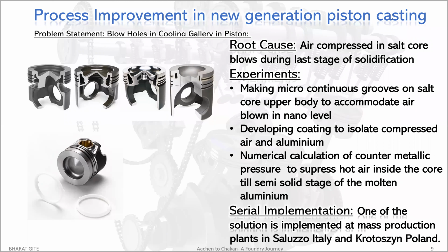Defects such as blowholes were observed in the upper side of the cooling gallery, and after a lot of effort, root cause analysis showed that compressed air inside the salt core was blowing at the last stage of solidification, leaving some small defects in the upper cooling gallery of the piston. We came up with 3 different solutions. The first was making micro continuous grooves on the salt core, called Rillen in German, to accommodate the micro level of air and gas during solidification. It was successful, not to the perfect extent, but successful.